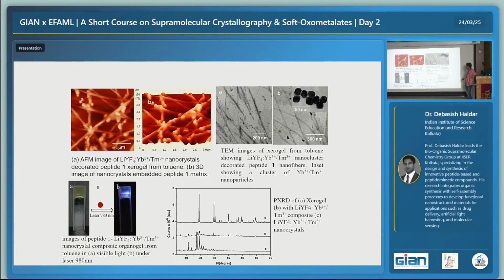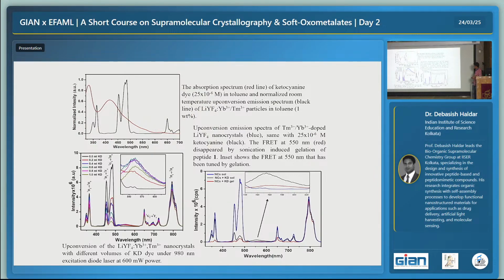And finally we have incorporated lanthanide nanocrystals in the gel matrix, and we figured out that the lanthanide nanocrystals finely self-assemble on the surface of the gel fibers, and we use that for upconversion studies. This is something interesting, that the lanthanide nanoparticle is showing the upconversion. Now we have doped with a ketocyanine. The lanthanide nanoparticle absorption is actually the emission of the ketocyanine. So where the ketocyanine is emitting, the lanthanide nanoparticle is absorbing that light. If we check with a very small amount of ketocyanine and this lanthanide nanoparticle, we can actually arrest that upconversion. That is exactly what is happening inside the gel matrix, but in solution state you cannot do that.